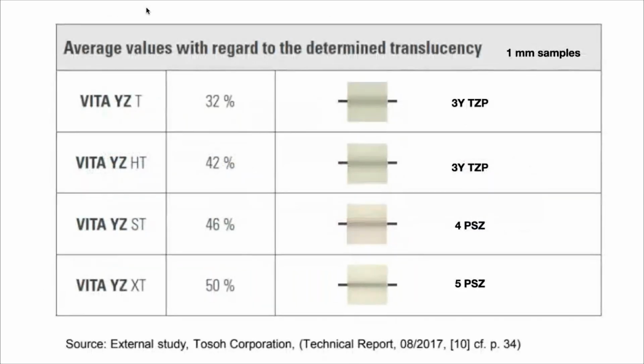So when you start to look at average values in regards to translucency, you start off with a millimeter sample. That's a fairly reasonable thickness for what? For a coping maybe? So when you start to look at the zirconia crowns, you have the T material, which is 3Y, and the HT, which is 3Y with a little bit less alumina, which increases the translucency, and the ST and the XT, 4 and 5, that really increases the translucency.